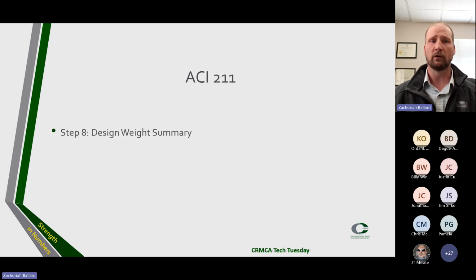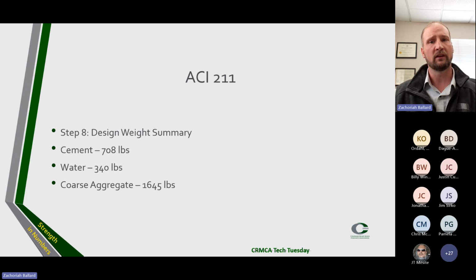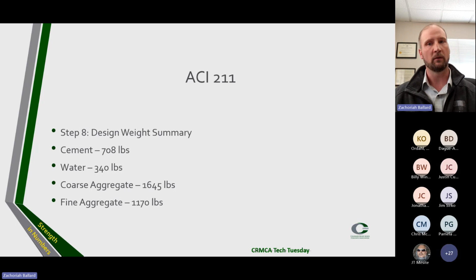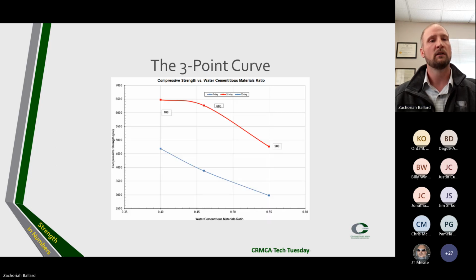So our step 8 is our design weight summary. So we have cement at 708, water at 340, coarse aggregate at 1645, and the fine aggregate at 1,170. And that's the mix design we take to the lab. Then we need to do it 2 more times at varying water cement ratios to develop a 3-point curve.